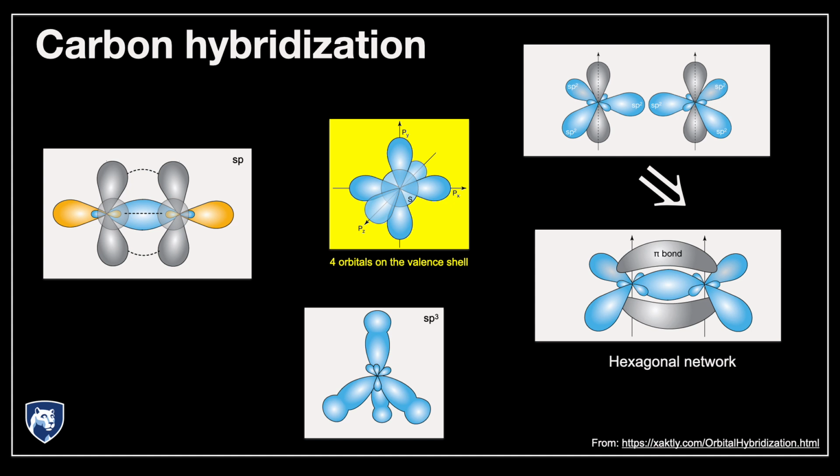left after hybridization. What's good about this is that by geometrical constraint, the blue bonding that we see in this picture takes place at 120 degrees, which is exactly the right angle for a hexagonal network. One of the reasons why it's so exciting is because a 120 degree hexagonal network corresponds to a close-packed system, which we see in nature very much, because close packing is seen in nature as a minimization of energy. So of course, nature has known that for a long time.